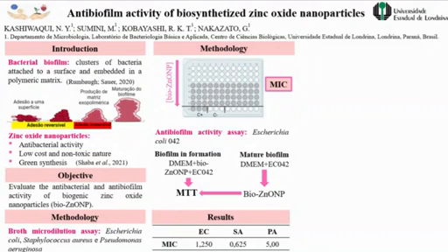The difference is probably related to the differences in the bacterial cell wall. The zinc oxide nanoparticles produce reactive oxygen species, which damages the bacterial wall. The gram-negative bacteria presents an external membrane that protects the bacteria against the reactive oxygen species, while the gram-positive bacteria don't have this membrane, being more susceptible to the reactive oxygen species.